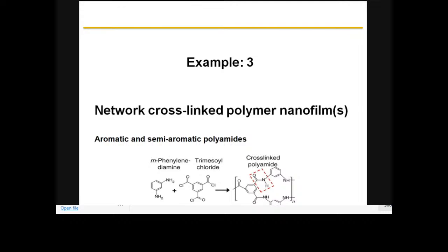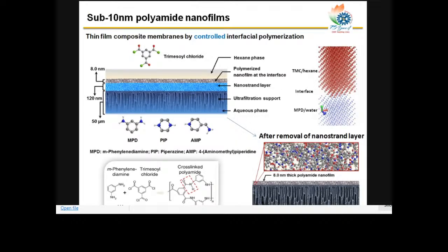The third example is a network cross-linked polymer, which we made by interfacial polymerization. Interfacial polymerization is a polymerization technique where the polymerization happens at the interface between two liquids. In our case, one is water and the other is hexane. We put metaphenylenediamine and trimesoyl chloride in the two different phases, and carry out the interfacial polymerization at the water-hexane interface to get a cross-linked polyamide structure. The idea was to make a polymer thin film via interfacial polymerization, and we managed to get a sub-10 nanometer polyamide nanofilm.